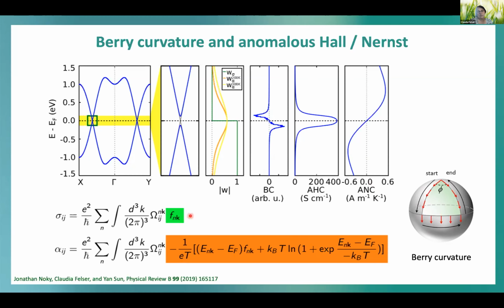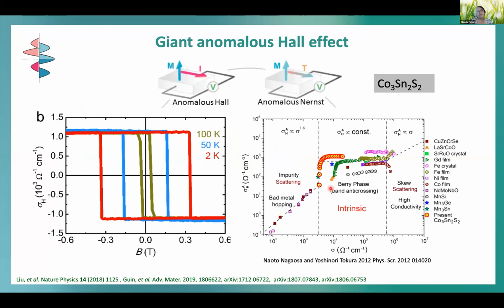This leads to an enhancement of the anomalous Hall conductivity and also an enhancement of the anomalous Nernst conductivity. The anomalous Nernst conductivity is the first derivative of the Hall conductivity, so it's much more broadly distributed around the Fermi energy—this is also what we see in the experiment.